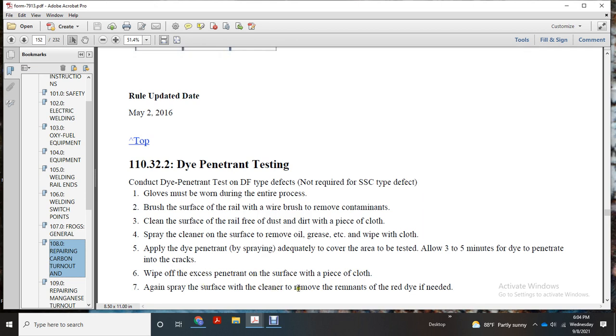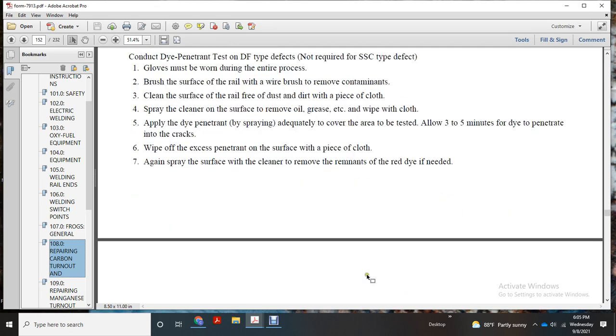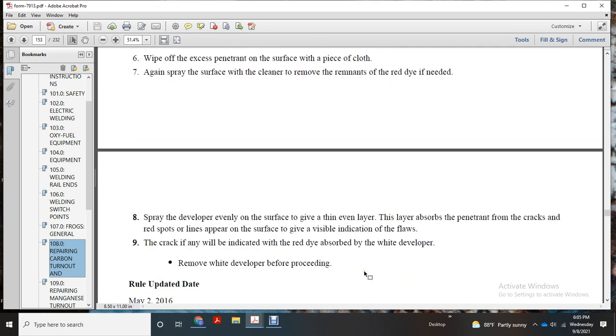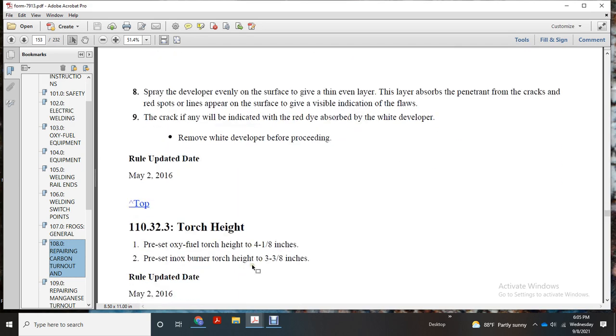Again, spray the surface with the cleaner to remove the remnants of the red dye if needed. Spray the developer evenly in a thin layer to absorb the penetrant from the cracks. The red spots or lines that appear give a visible indication of the flaws. Cracks, if any, are indicated with the red dye absorbed by the white developer. Remove the white developer before proceeding.